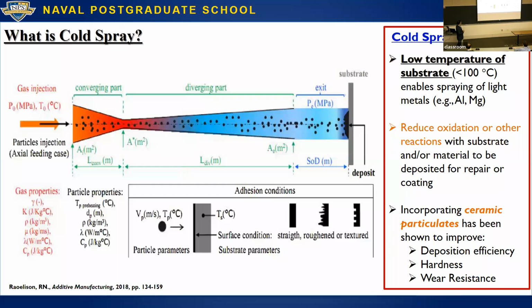This is the additive technique that we're using here. We start with very similar powders as I discussed earlier. This technique is a little bit more robust in that you can get away with not having perfectly spherical powders. You can have very elongated particles. You are driving them with a pressurized gas, so that helps them flow, as opposed to the 3D printing system that is essentially gravity fed.